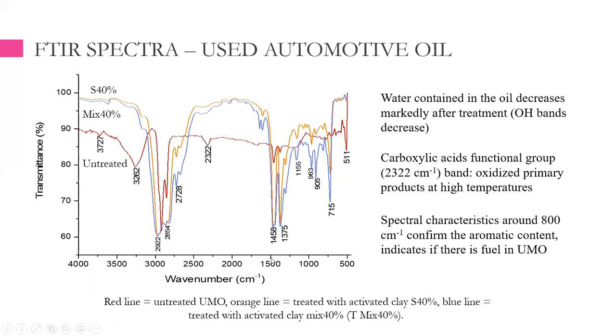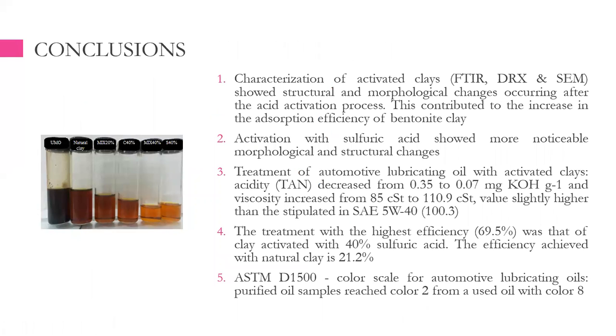So, as a conclusion, we can mention that the characterization of activated clays using, in our case, infrared spectroscopy, X-ray diffraction, and scanning electron microscopy showed the structural and morphological changes that occurred after the activation processes. This activation contributed to increase the adsorption efficiency of the bentonite clay and to remove the contaminants of the used motor oil.